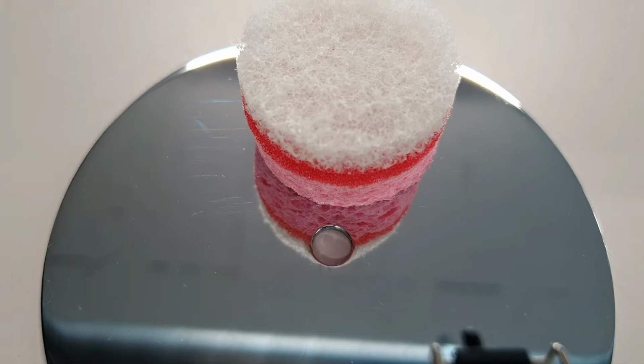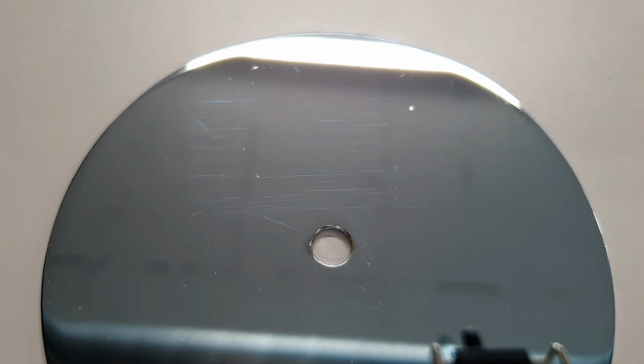We have successfully completed the first test series with the Scotch-Brite soft scrub, which claims to leave no scratch marks on the surface. The sample we see here is the electroplated chrome. We see slight scratches if we have the light on the right position, but it's definitely not bad. All the other samples, the PVD coatings, were fine. We did not see any scratches at all.